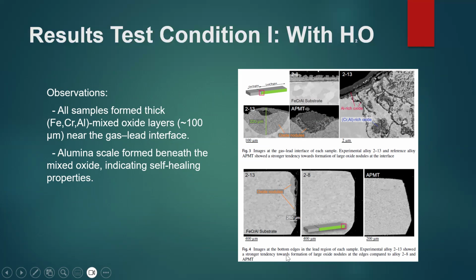This image shows the bottom edge of the lead region for each sample. Experimental alloy 2-13 showed a stronger tendency toward formation of a nodule layer at the edge compared to alloy 2-8 and APMT. We can see the different side nodules for sample 2-13, 2-8, and APMT.